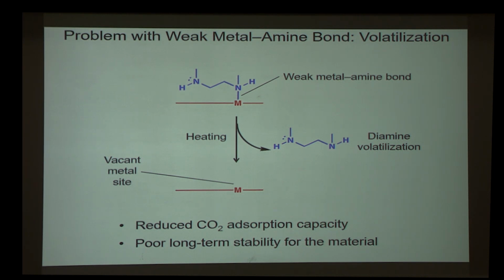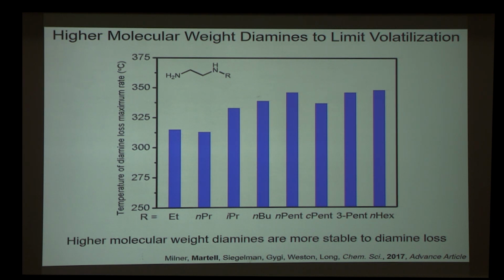But in the course of the experiments, I found that this created a serious problem. When we heat up the sample, which is necessary to release CO2, I found that the diamine was prone to volatilization. It would transition to the vapor phase and leave the material permanently. This leaves behind vacant metal sites, and it corresponds to reduced CO2 adsorption capacity because we rely on those amines for capture of CO2. What this corresponds to is poor long-term stability in these materials, and we needed to improve on that. The strategy we used to improve the stability was to use diamines with this type of structure.